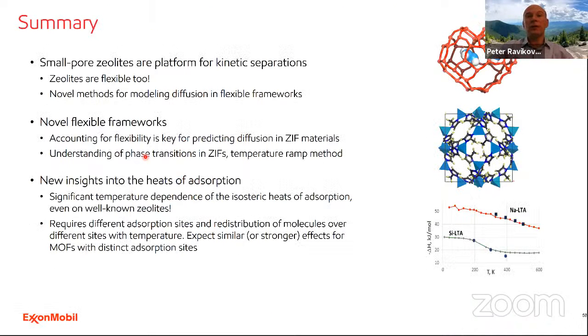So this is my summary. We talked about the small pore zeolites for kinetic separations. I demonstrated that zeolites are flexible, and this is a very interesting area to focus on. I showed some novel methods for modeling diffusion in flexible frameworks, and generally flexible frameworks are a very interesting area. Novel flexible frameworks, so-called zeolitic imidazolate frameworks, are much more flexible than zeolites, and also it is much more common to see phase transitions within materials of this type.